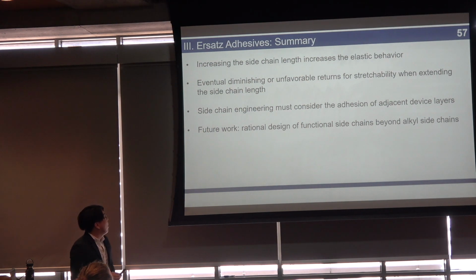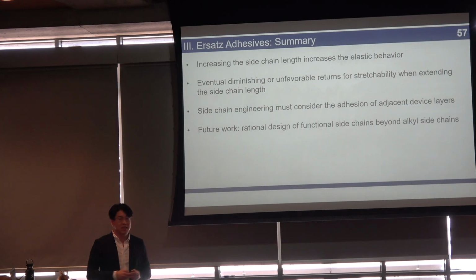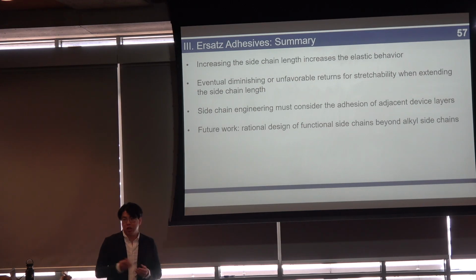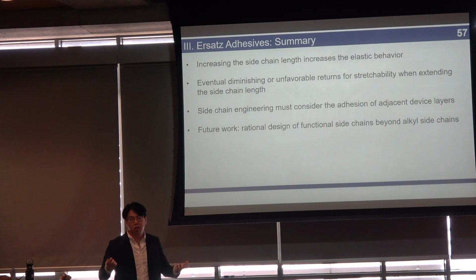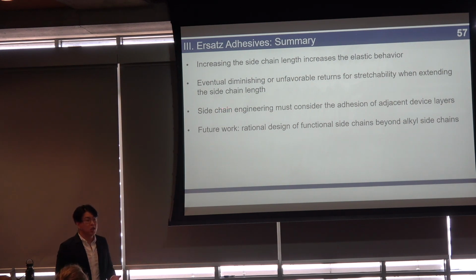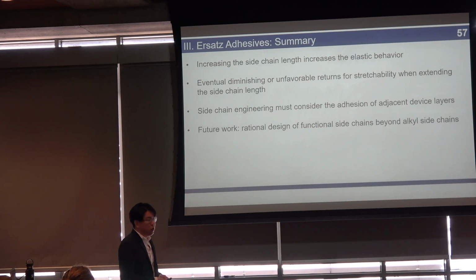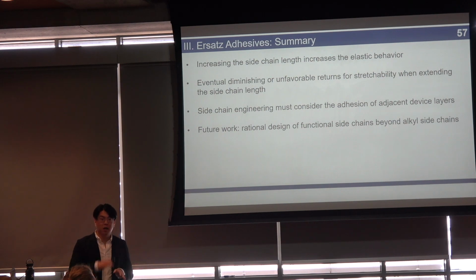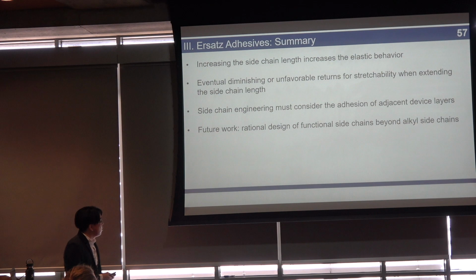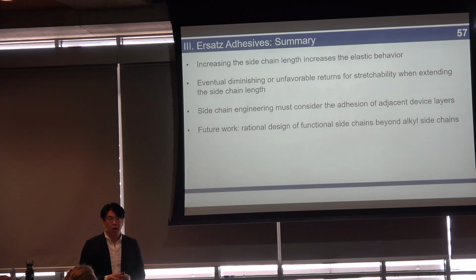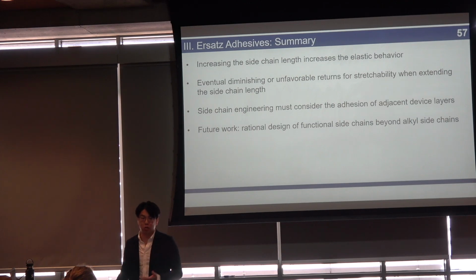So this taught us a little bit about the adhesive properties of our materials, and we saw that increasing the side chain length generally increases the elasticity of your material, but unfortunately this doesn't represent a good strategy in terms of stretchability if you want to make a stretchable polymer. One common method that chemists use to increase the fracture strain of these materials is just to make a longer side chain. But we showed that this eventually has diminishing or unfavorable returns. Furthermore, if you're engineering your polymer, you have to consider how it's going to adhere to your bottom layer as well as your top layer, right? So, for example, this might be important for designing a polymer with better functional groups and better functional side chains than just an alkyl chain.